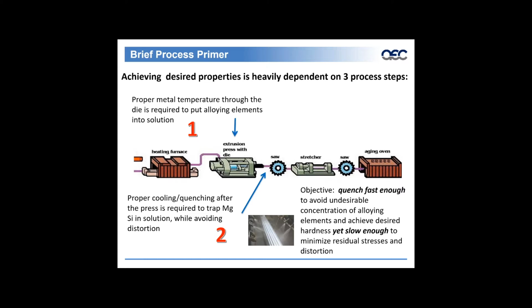Now with a 6005A or a 6061 or a lighter wall 6082, that requires a more aggressive quench rate. So now we must introduce, in addition to air, we must also introduce water, and this is called an air-water mist. So more distortion relative to our 6060, 6063 low mag silicon alloys, but less distortion than a full water wall quench of a 6082. Okay. Then our third band of alloys, which is the higher mag silicon, an example of that would be a 6082 alloy.